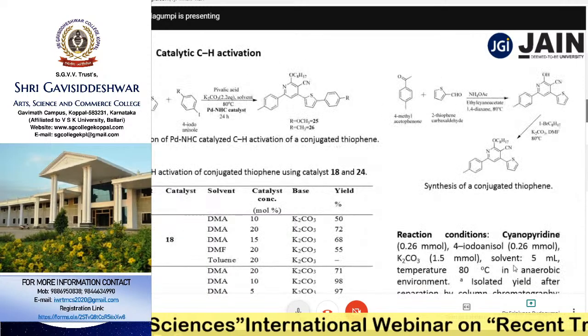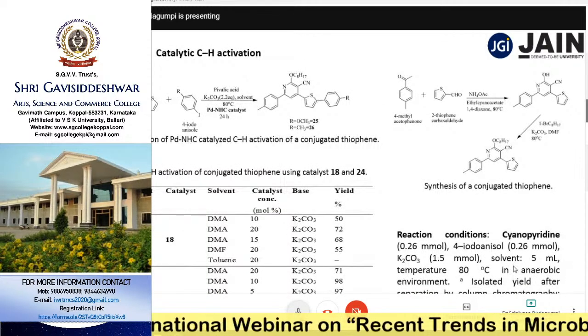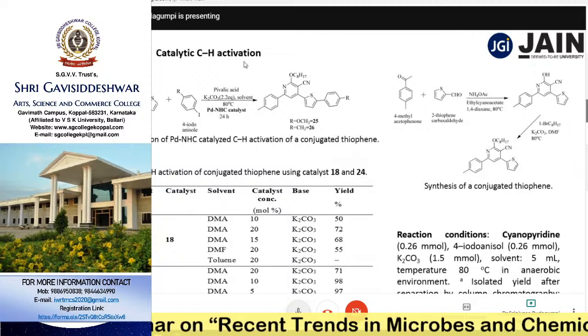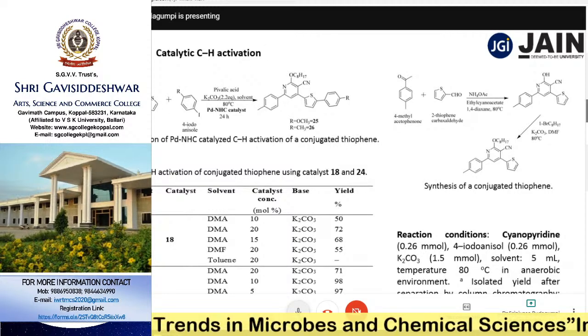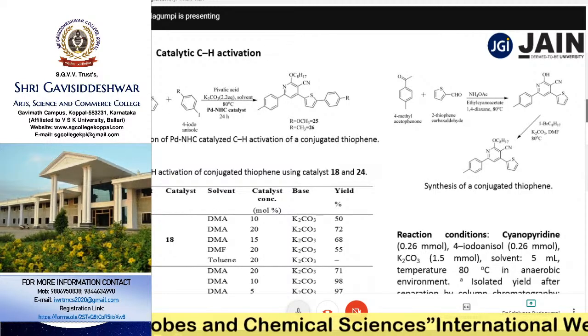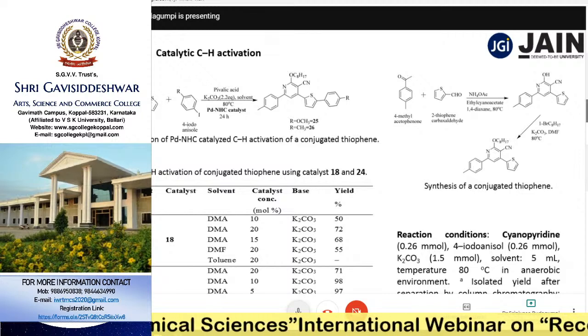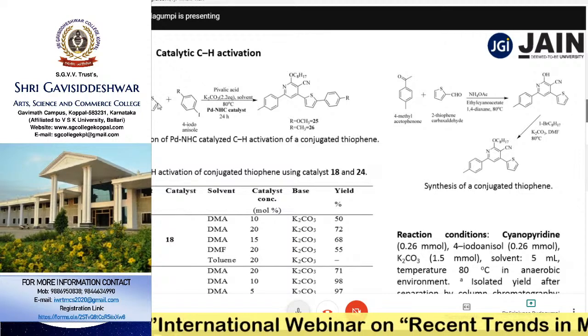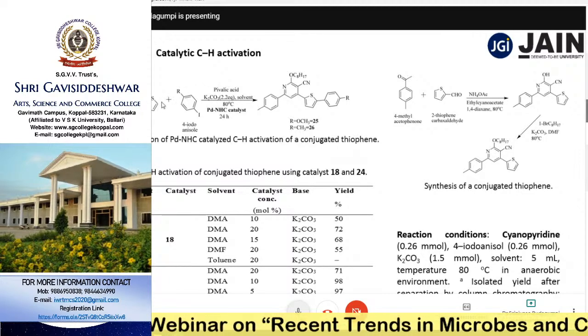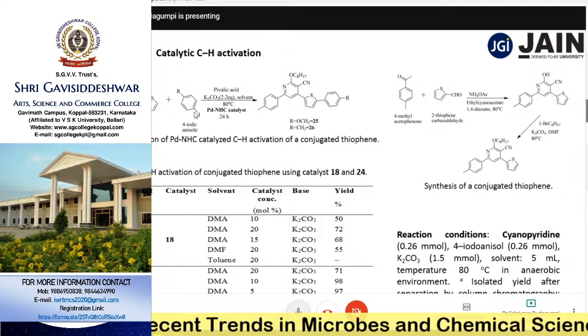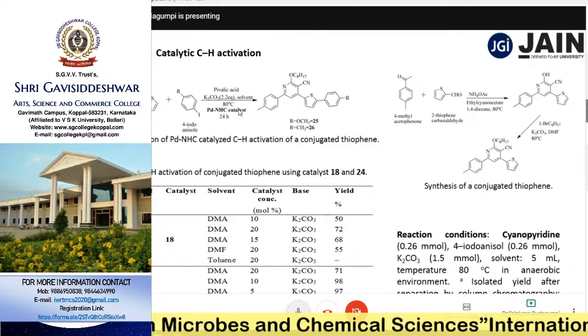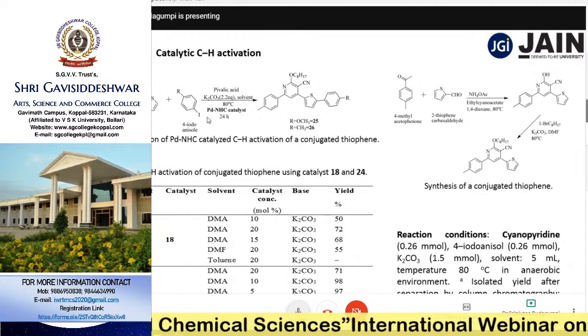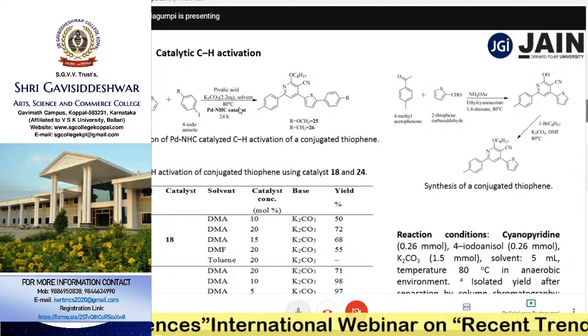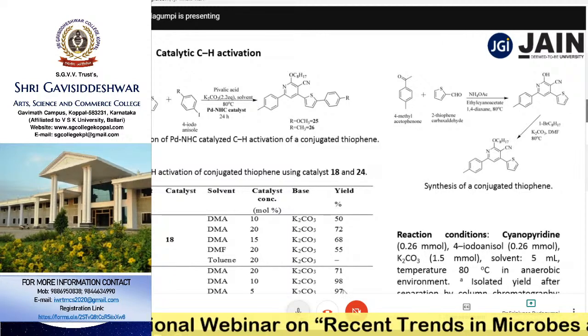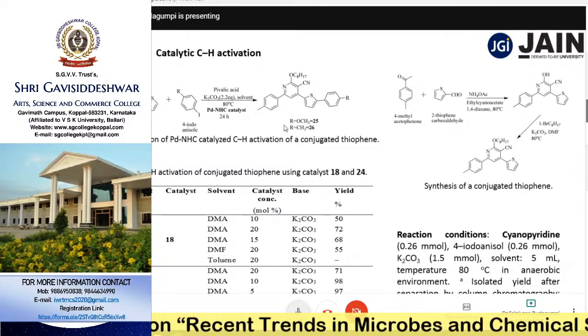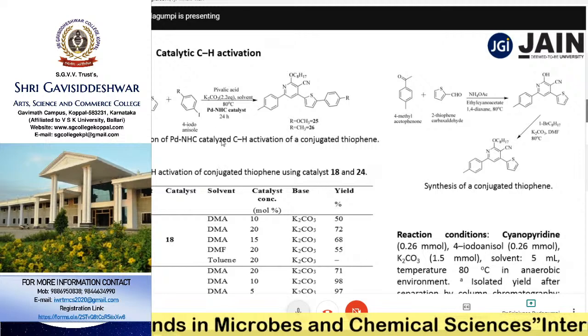Further, the same complexes have also been evaluated for C-H activation catalysis. This is a cyanopyridine derivative which has a thiophene substitution. This thiophene can be arylated at C5 with the help of an aryl halide in the presence of these palladium catalysts. This direct arylation using these palladium complexes has given us 97% yield, especially in the case of pyridine coordinated complexes.